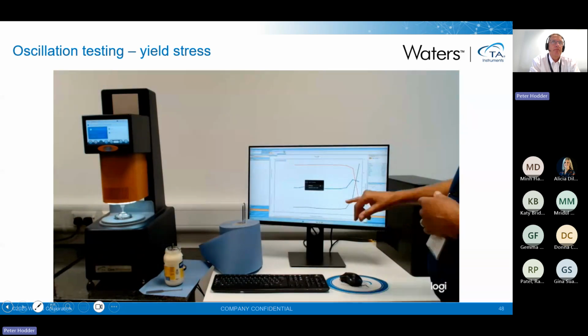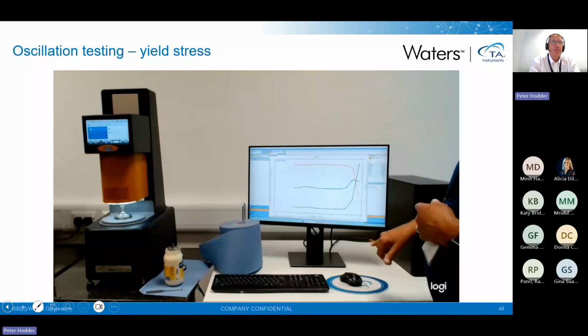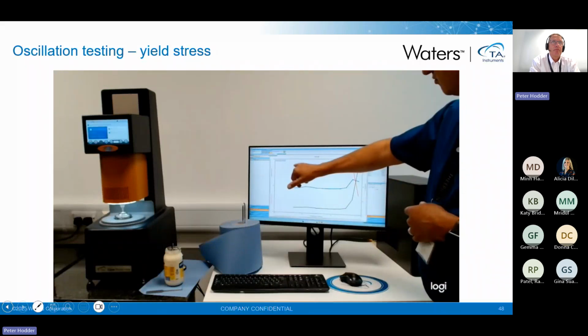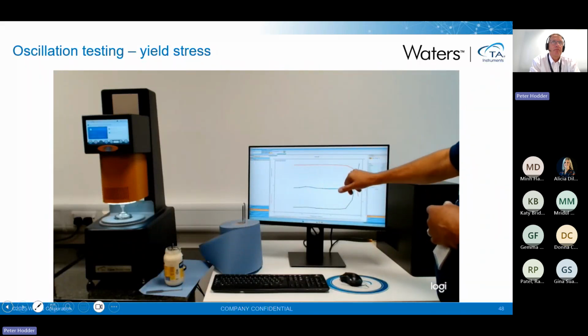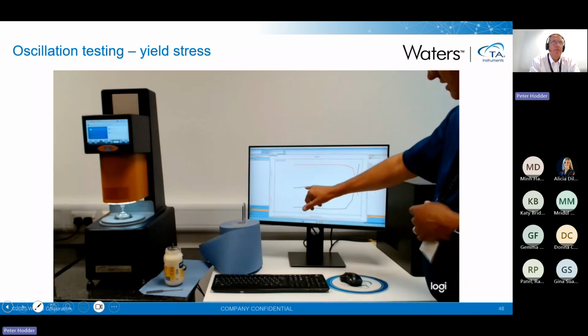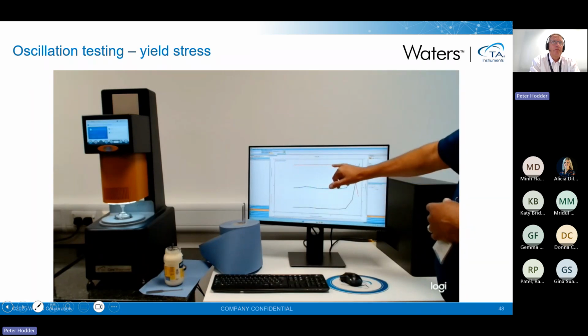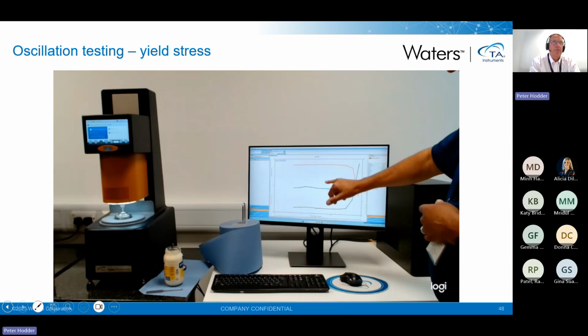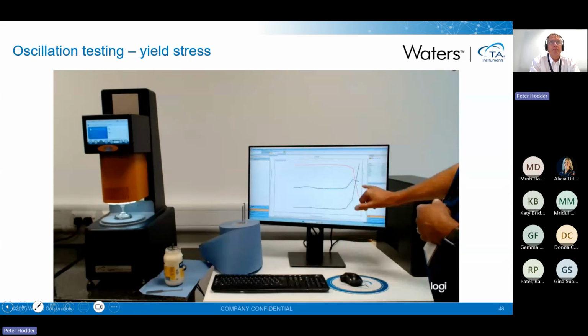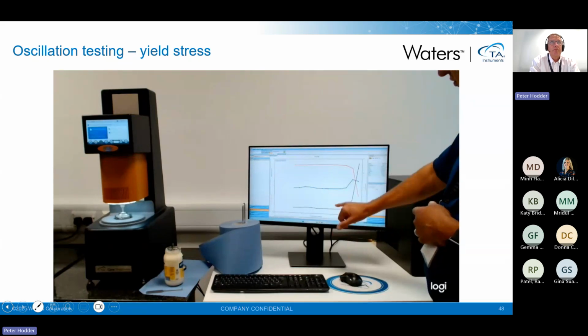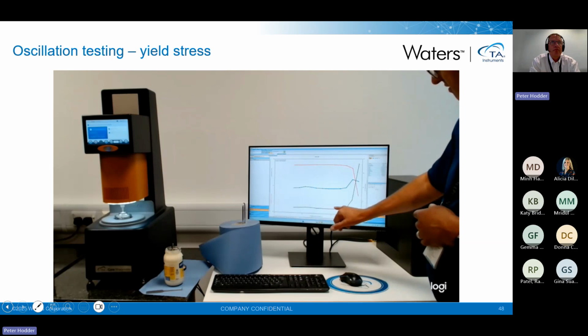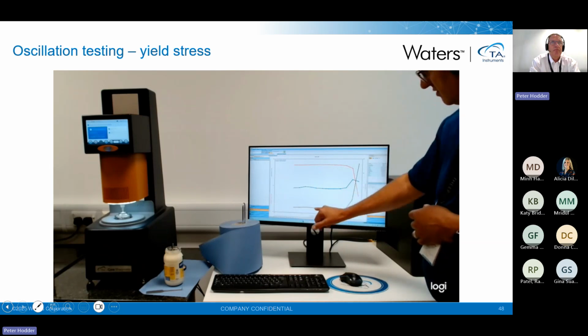The graphic shows, hopefully once that monitor label goes, that the red line represents how solid-like the material is. The blue line, how liquid-like the material is. In this case, this sample is very elastic dominant, hence why it's wobbling on the spoon. The phase angle, the ratio between the two, is down here at around 8 to 10.